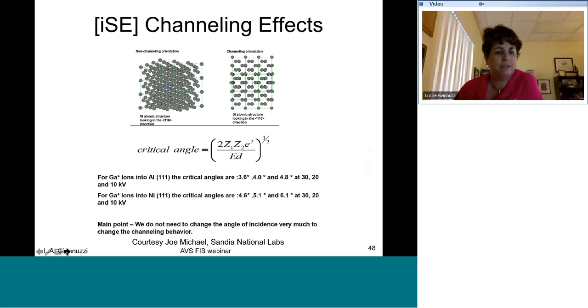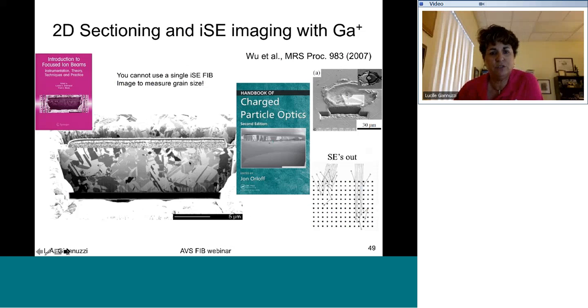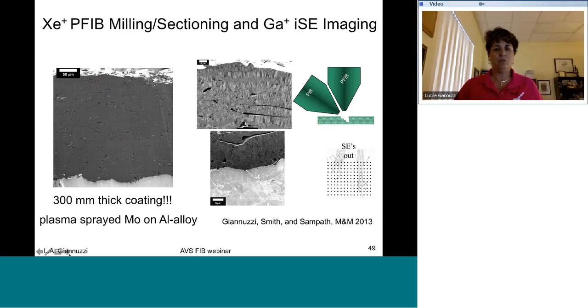Grain boundaries are typically defined by 10 or 15, 12 degrees, however you want to define a grain boundary. So if you tilt only a few degrees and you see the contrast changing, then you know that it's more strain related versus actually grain related. That's how you can really define whether you've got grains or just strain, for example. There's no reason why you can't do plus or minus 5 or 10 degrees and find out really quick what you've got there.